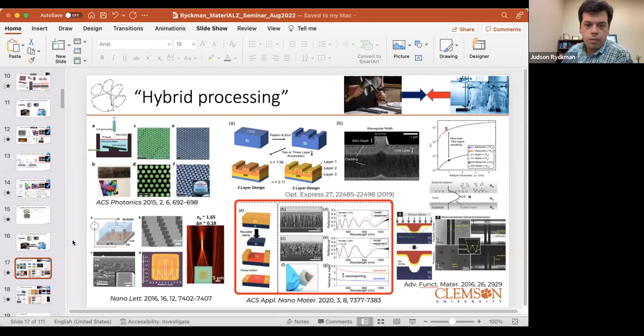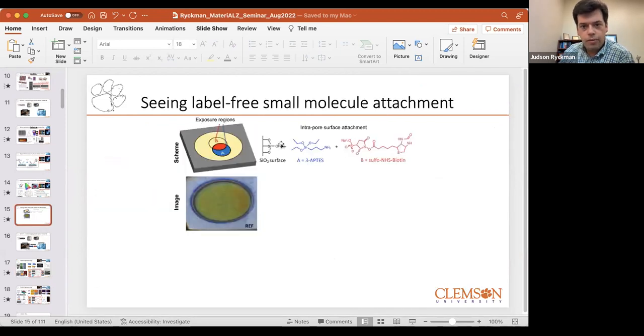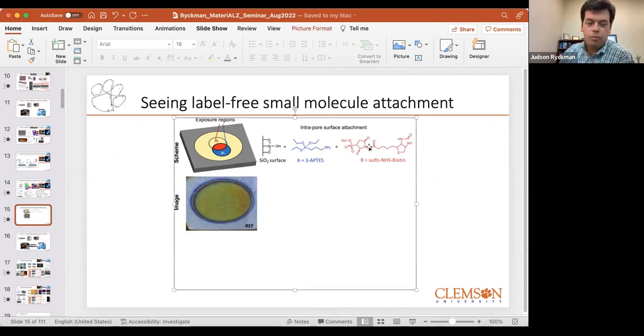And very quickly, you only looked at physically adsorbed layers, right? If you have chemically adsorbed, where there's charge transfer or something, that could also in principle shift. Yeah. So we do tend to look, say, if we're doing binding of molecules to the surface, we're using the fact that this APTES molecule or this biomolecule has a refractive index that's larger than the medium it's displacing. So we really use that effect. We haven't done too much with charge, although there are charge corrosion effects that occur that could amplify in some cases, but mostly just refractive index based.